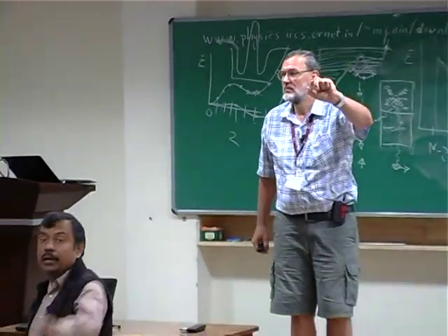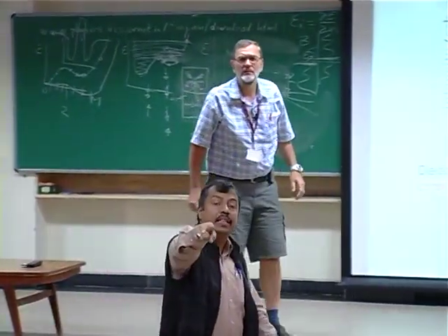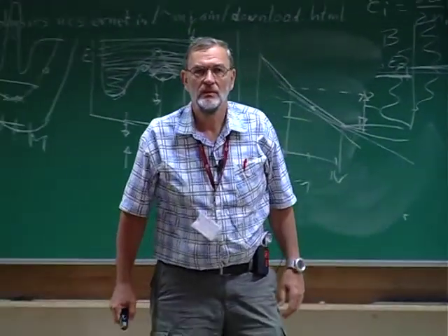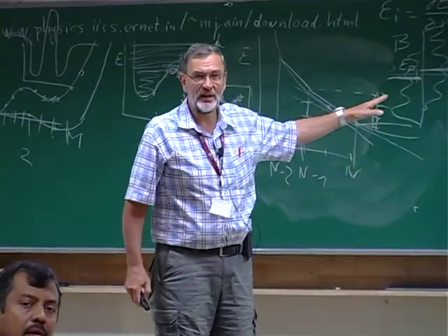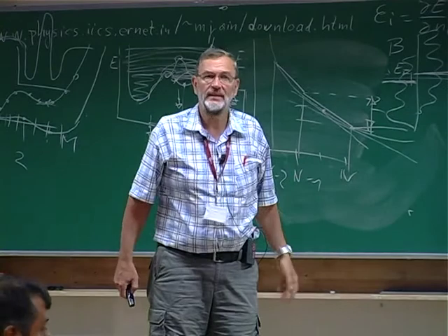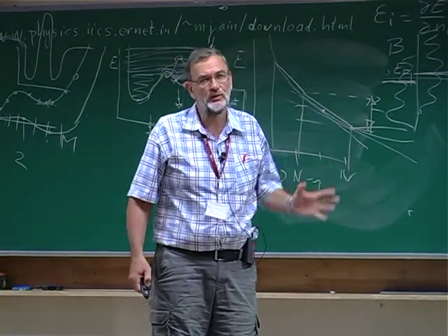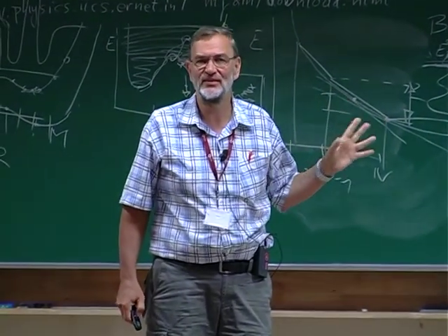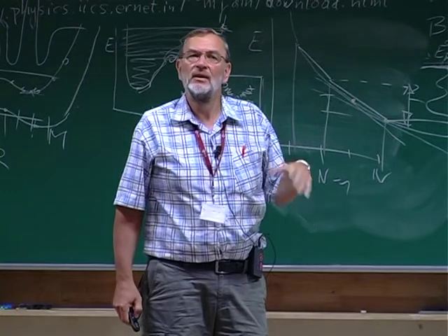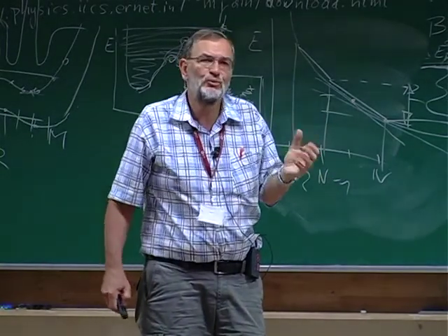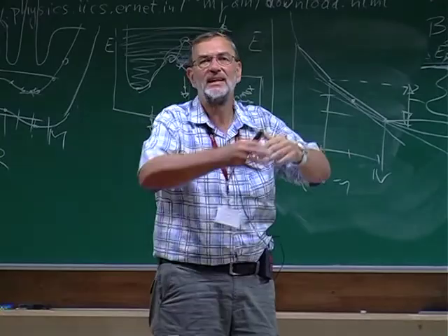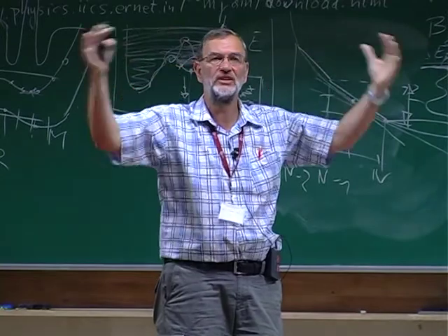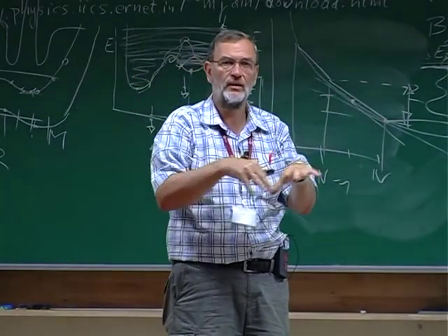The amount of hole created. How much does it depend on that? For core hole spectroscopy, it depends on that, yes. If you really want agreement with experiment, it's also not always clear that one core hole is the best. From the theoretical point of view, you should probably have one core hole in as large a supercell as possible, because the other atoms can then contribute to the screening of this hole.